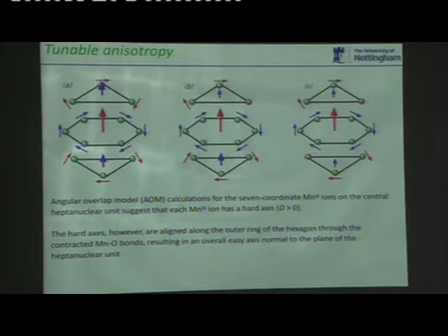Because if you have manganese 3, you're talking about 4 d electrons. You have manganese 4, you have 3 d electrons that you can use for magnetism. And what we found is that essentially the manganeses that oxidized were up in the top triangle or bottom triangle as we look at the molecule simplified.